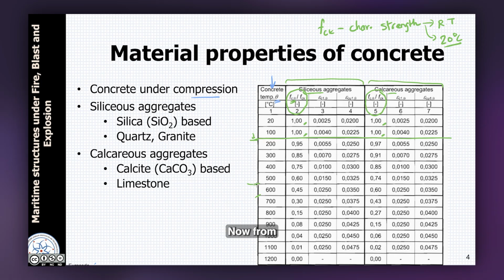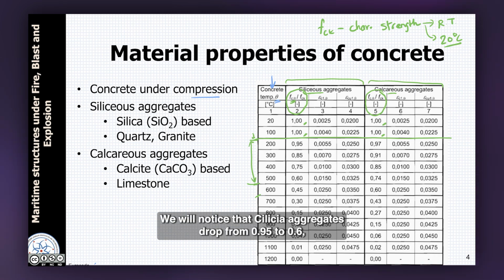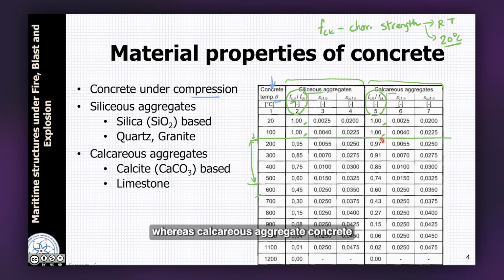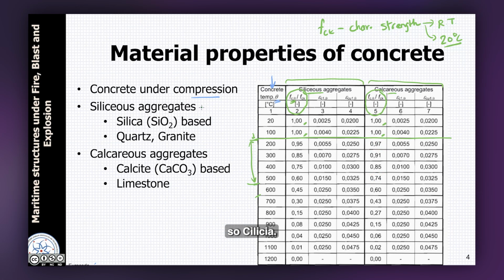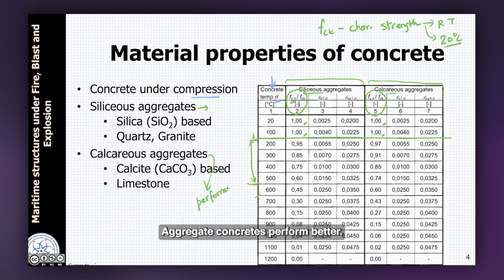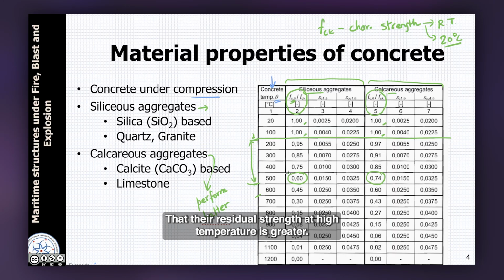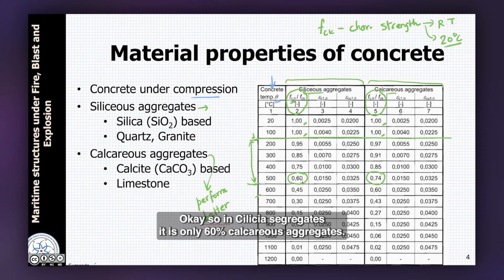Now from 100 to 500 degrees Celsius change, okay, we will notice that siliceous aggregates drop from 0.95 to 0.6, which means the strength becomes 60% of its original strength, whereas calcareous aggregate concrete drops from 0.97 to 0.74. Okay. So siliceous aggregate concretes, calcareous aggregate concretes. Okay. So calcareous aggregate concretes perform better. And what do I mean by perform better? That their residual strength at high temperature is greater. Okay. So in siliceous aggregates it is only 60%, calcareous aggregates it is about 74%.